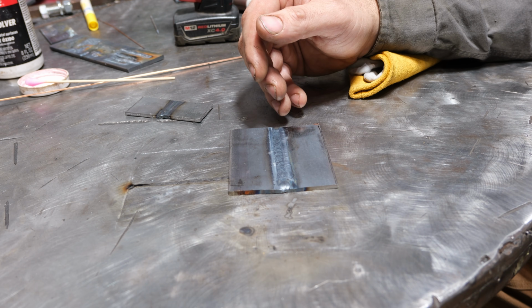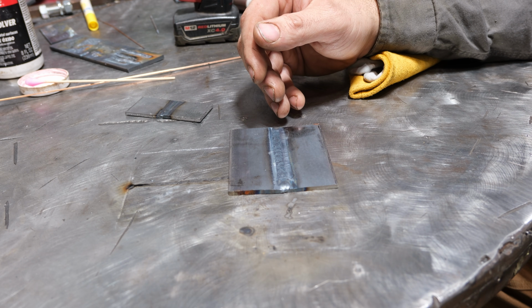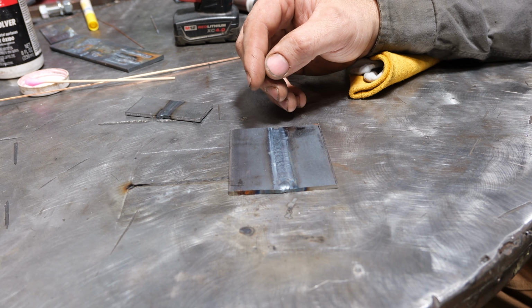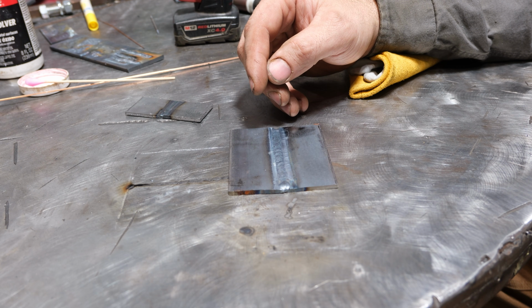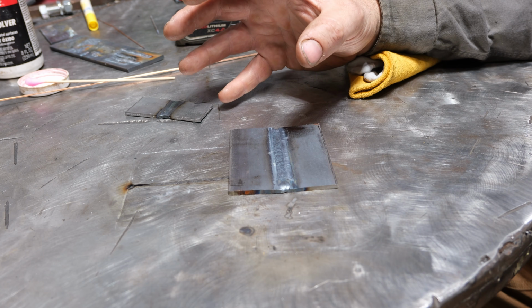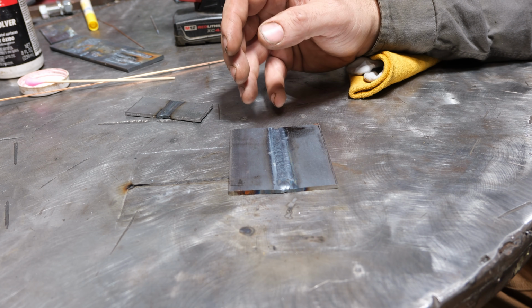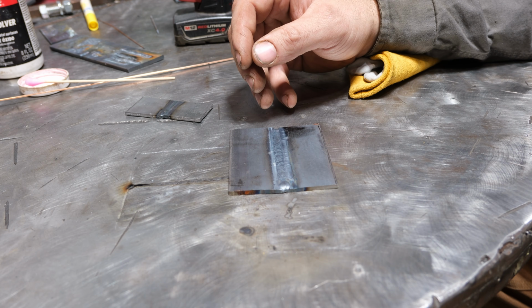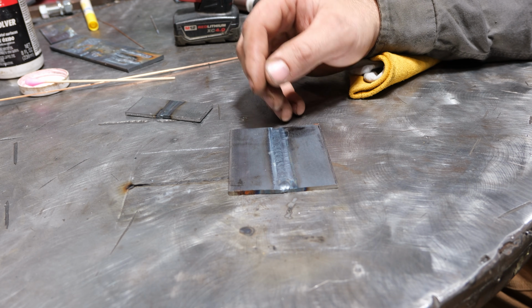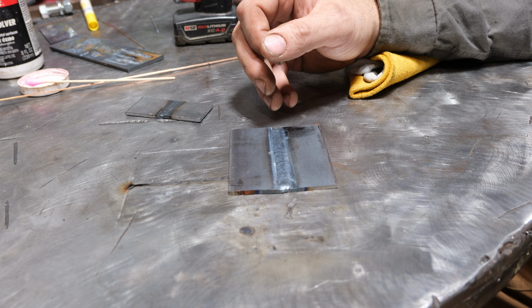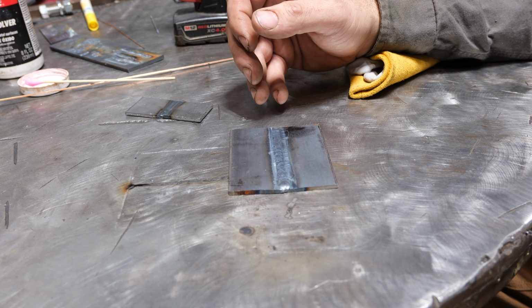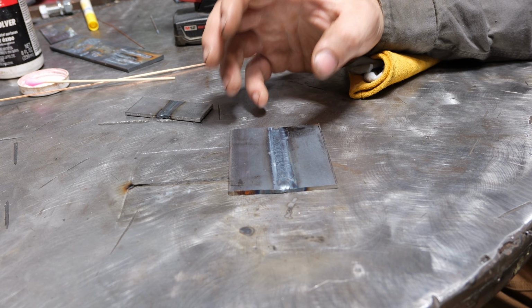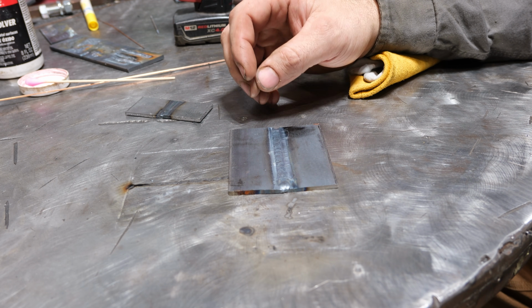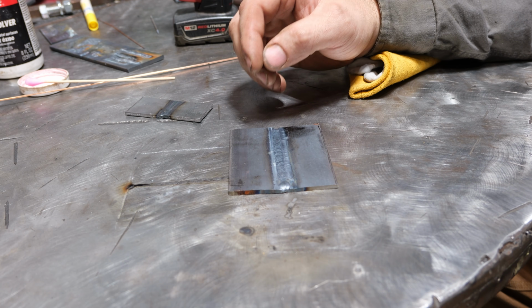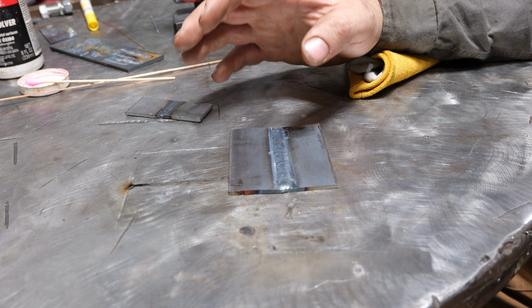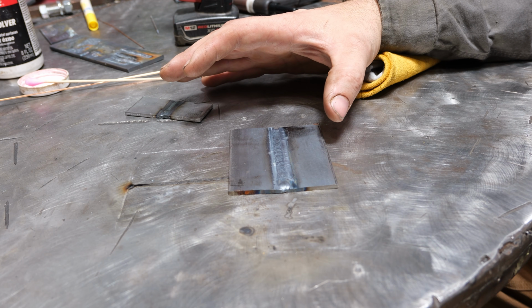One of the issues I had is that limiting myself to 120 amps, if I tried to push any more filler rod into that, the molten puddle would have quenched, and then I would have had to slow down even more than I was, which would present issues. So I should have been up at 130 to 140 amps, been pushing more filler, and then I could have easily brought it out past flush on the face, plus having really good fusion on the inside. So there is an issue with amperage where if you don't run enough, you are not going to have very good success doing this. All right, well, I think I covered enough about the overview of doing butt welds.